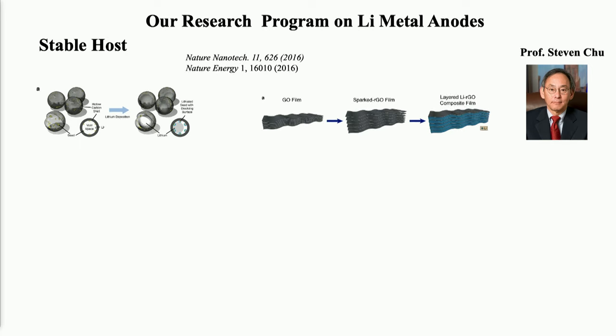When Steve came back in 2013 from the Department of Energy, he and I brainstormed about how to solve this problem. The first idea we came up with is to build a stable nanoscale host, hosting lithium deposition inside so it doesn't go everywhere. So we offer a seeded approach to control lithium nucleation inside a hollow carbon structure, and also control lithium nucleation and growth between graphene oxide layers. That has provided quite exciting progress towards solving this problem.